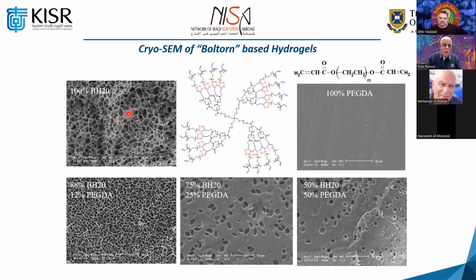So you don't want it to be extremely porous because it means it's going to degrade very, very fast. So we don't want to use it at 100%. We have to use it in combination with something else. If we use it with polyethylene glycol diacrylate, then this is going to slow down the degradation rate. So that's why we introduced the tri-block copolymer with the lactide, with the polyethylene glycol in the middle, in order to modulate the swelling as well as to modulate the degradation rate.